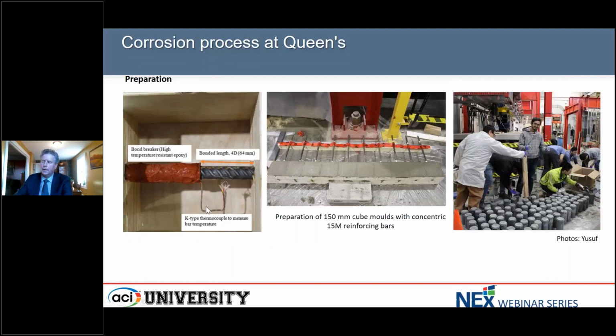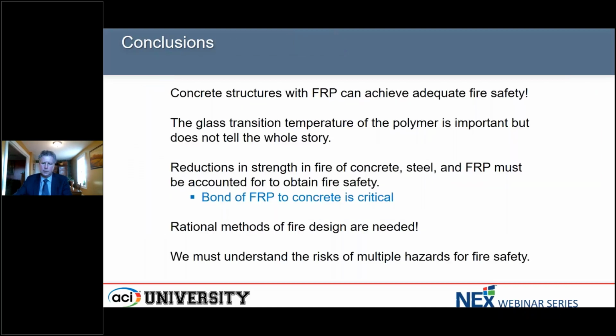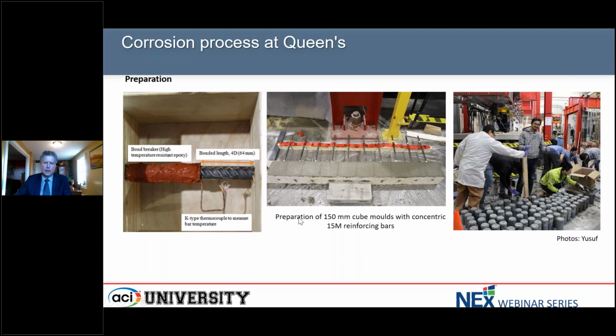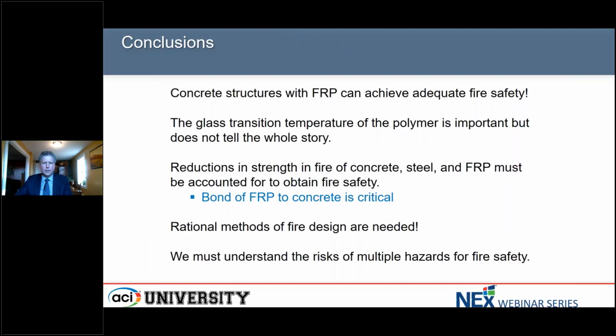And so you're seeing when we have corrosion. You can see how we're setting up these pullout specimens for testing, and then exposing those into corrosive environments and corroding them at certain levels, and then testing them at high temperature to see how that corrosion has affected the bond performance. So that brings me close to the end of my talk today, and I just wanted to wrap up with a few points and conclusions. The first is that concrete structures with FRP reinforcement, we can have adequate fire safety, but we have to understand what's going on with the materials and what happens at high temperature.